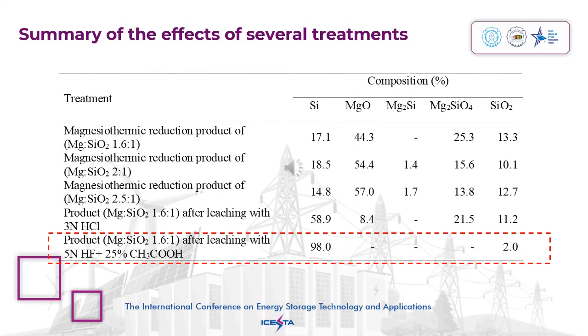Summary of the effect of several treatments. It can be concluded that the purification treatment applied to remove impurities from the silicon product was successful, with a final silicon purity of 98%, showing its potential to be used as lithium battery anode material.